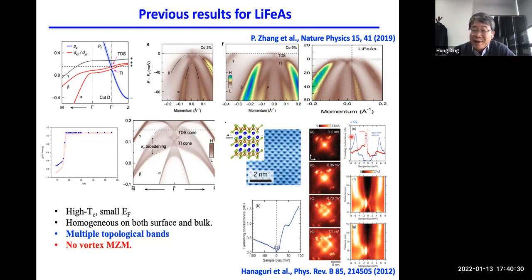So the surface is not so good. This has a non-polar surface, with one mass bonding between the two lithium layers. So we said, this would be a fantastic platform for Majorana zero mode. But it turned out this material has no zero mode, as shown by Hanaguri back in 2012, who saw a peak not at zero. This is an ordinary CdGM bound state from the bulk state.